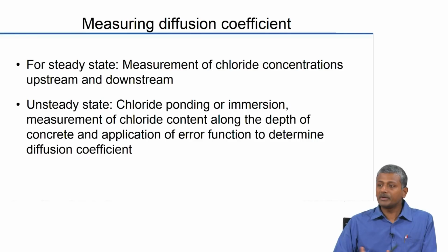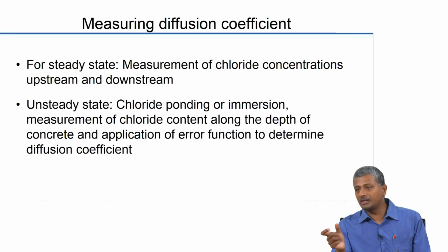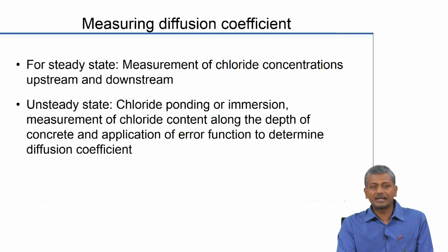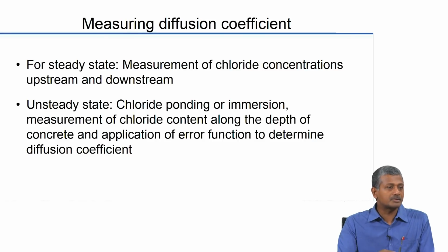Now how do we measure this diffusion coefficient? As far as steady state condition is concerned, all you have to do is measure the chloride concentration upstream and downstream. You know the thickness of your material. You apply Fick's first law, and you can directly get your diffusion coefficient, okay. But that does not work in the case of materials like concrete with changing characteristics with respect to time. For the second law, for unsteady state diffusion, we need to do chloride ponding experiments.